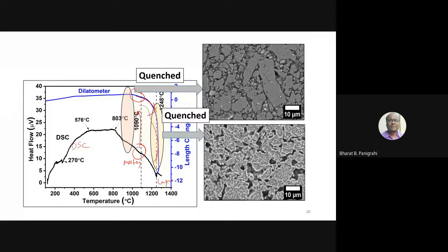And if you look at the microstructure, as we are interested more in microstructure, as I mentioned earlier, you heat the material here and quench. We heat the material here and quench. Whenever you quench at different temperatures, let's say somewhere around 800 degrees centigrade, you can see the grains are unsintered. Very clearly grains are there. But if you heat it at high temperature, somewhere around 1200 degrees centigrade, you will see these are grains, and the white phases you see are basically an indication of wetting of the surface by the liquid phase. It's just like something you have dipped in the liquid. After the dipping, you will see that liquids are there. You can see very clearly the liquid is quenched.